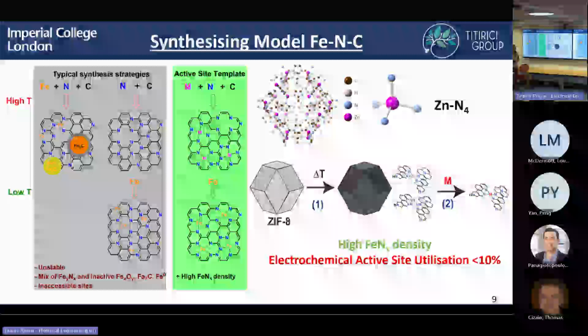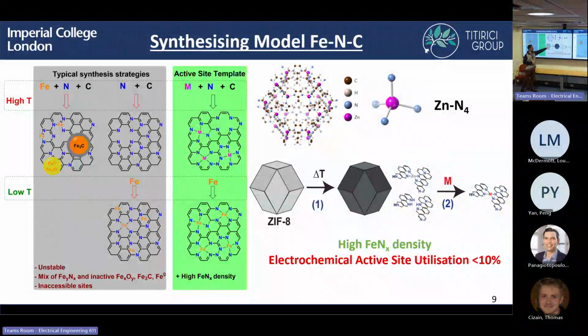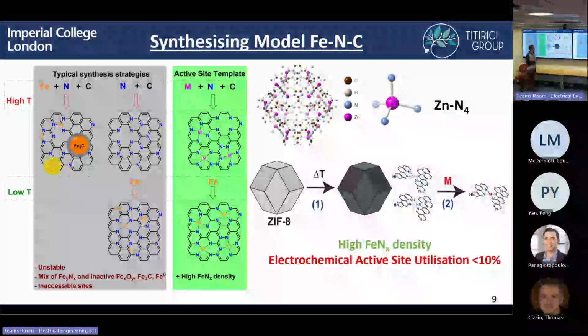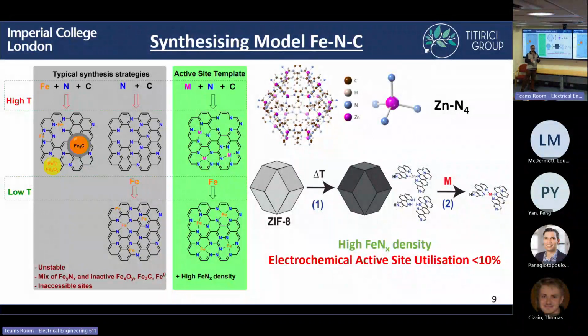The benefit of this is that the ZIF-8 structure has a really high concentration of zinc, so you can end up with a very high concentration of active sites. The problem is, what's been shown in the literature is that the electrochemical active site utilization is less than 10%. So while you can have a very high number of active sites, you're not really utilizing most of them. This comes from the fact that this type of ZIF-8 structure is purely microporous, and so you limit the accessibility of the active site, since you need a combination of mesopores and macropores as well to really open up the pore structure and ideally utilize all of your active sites.